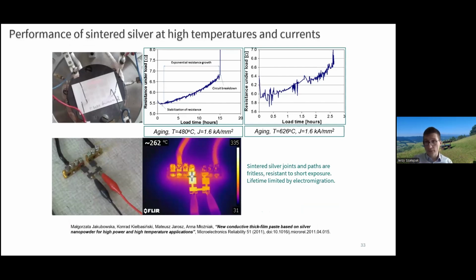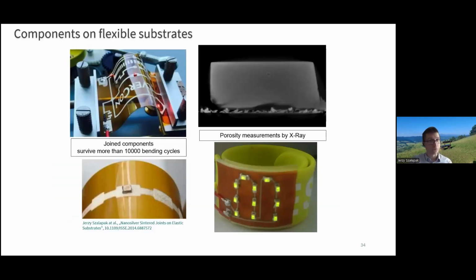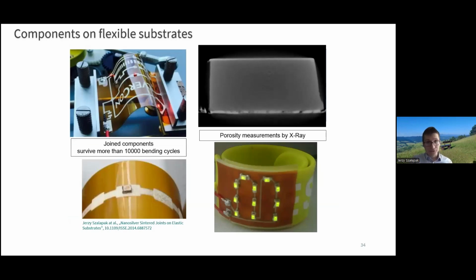Such joints can survive easily 350 degrees. The layers would survive up to 600 degrees, even though they were sintered in lower temperatures than we used later on during our tests. We used even 30 ampere current for the test. And going to the end, that was the biggest surprise, and that is why I'm speaking of this technique right now.